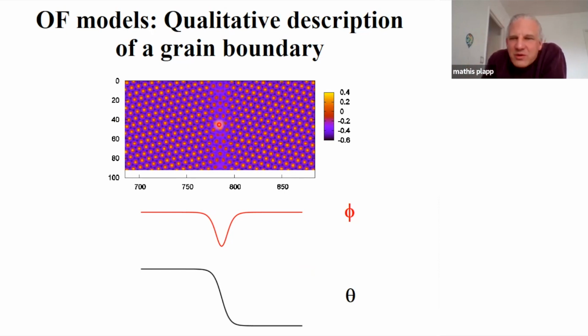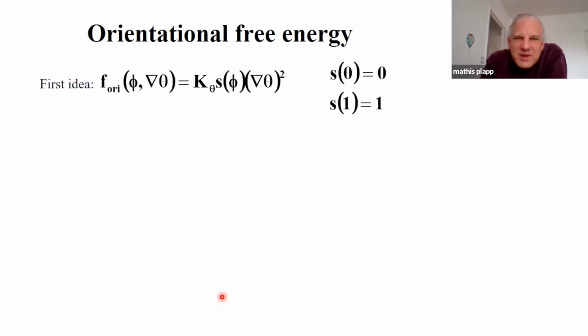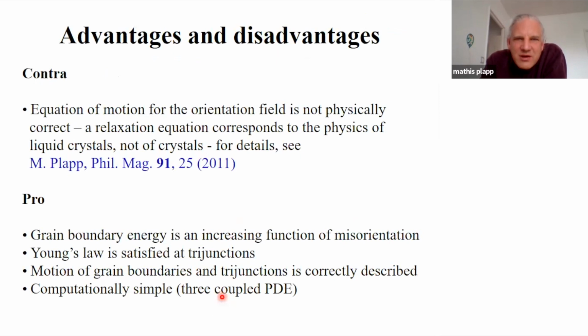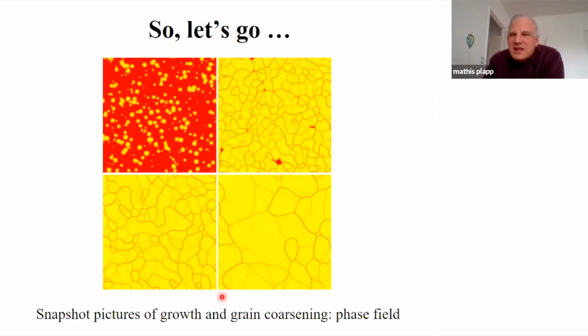So if I define my order parameter, which is still the phase field, then it has one value in the grains and it has a dip in the grain boundary. And the orientation field, on the other hand, has to have one constant value in one grain, one constant value in the other grain, and have a localized variation of the orientation inside the grain boundary. Now, to construct such a model is actually not entirely trivial. I had prepared some slides on that, but I will skip them because in the end, the only thing that is important is that it works.